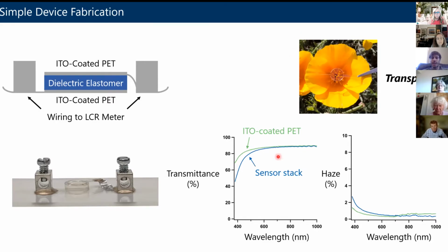Basically, the sensor stack, so all of this stuff combined, has a transmittance, has a transparency, if you want to think about it like that, that's very, very similar to the electrodes we've selected. The electrodes are the ITO-coated PET in green. It's really close across the visible to the sensor stack itself. So our material, that blue stuff, the dielectric elastomer, is pretty transparent.